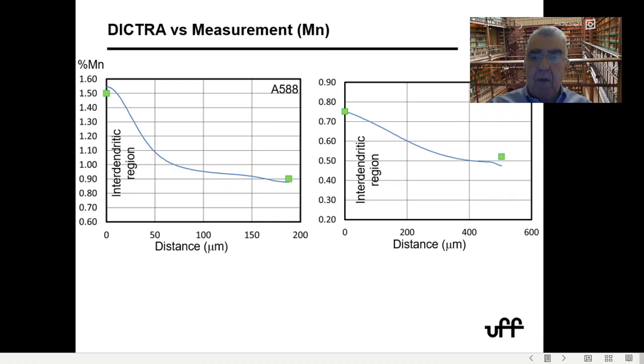So you see that DICTRA models the segregation fairly well, and I just chose manganese to present here because we did all the microprobe using manganese. And you can see right away that not only is the modeling good, but also a byproduct of this modeling is that if you increase manganese and if you increase carbon, which is the case with this steel, you get much, much more segregation. It is going to be a problem for your niobium, a problem for your titanium, which are also going to segregate when they are pushed by the liquid.